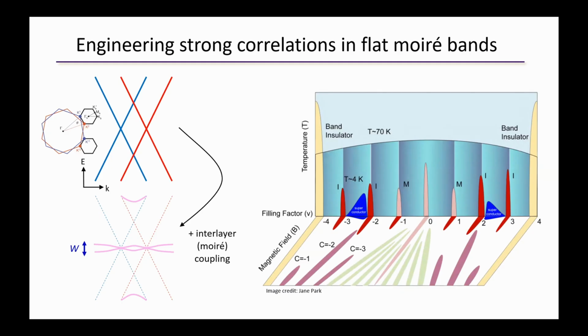At low temperatures on the order of a few Kelvin, you can start to break the spin and valley degeneracies of the system and get Mott-like insulators at integer fillings. If you go to 2 electrons or 2 holes per moire unit cell and add a bit of extra charge, then you get domes of unconventional superconductivity. And then if you apply a magnetic field, you can change the topology of the correlated insulators and generate a cascade of Chern insulators with Chern numbers 4, 3, 2, 1, depending on their apparent band filling factor.